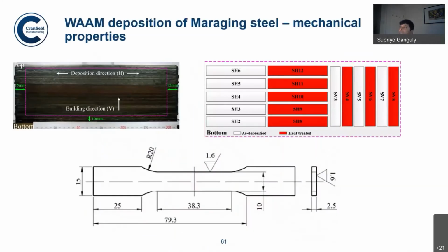But most importantly, this is the tensile test. A number of tensile tests in horizontal and vertical directions were carried out, just to show you the amount of testing. The red ones are heat treated, and the other ones are in as deposited condition, and we have tested to cover the entire length of the wall, the build direction, and also vertically.